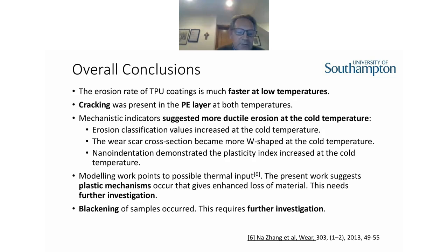The blackening, and if you look at the literature, there is some work suggesting that very locally there are thermal inputs possible here, which may well explain some of the processes. So it may be that local heating means that the polymer behaves quite differently to what we were expecting, and plastic mechanisms occur giving enhanced loss, and it might correlate to the blackening of the samples as well. There are other possibilities of stress wave reinforcement or shear stresses that might be explaining the cracking of the polyethylene